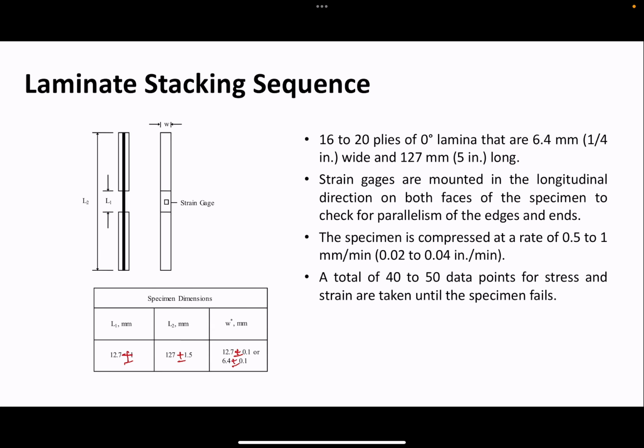So here the ASTM standard we follow is, I believe, ASTM D3410. So it says we have to use 16 to 20 plies of 0 degree lamina that are 1/4 inch wide and 5 inches long. Why do we have short stubby specimens with a lot of plies? Because we have seen the possibility of buckling happening, so we want to avoid that long length. And also, if the cross section starts bulging out, if it's too thin, that might not happen. It's not a good setup. That's why we want it to be thick to allow for the bulging of the specimen.